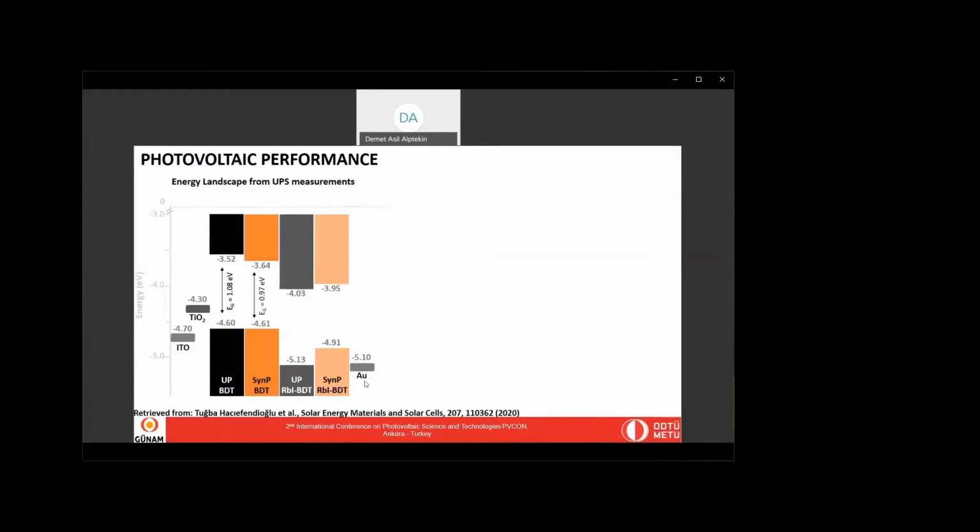This shows that unpassivated quantum dots have lots of surface defects which are healed during that thin film formation, and this leads to a huge downshifting of the energy levels, which is not severe for synthetically passivated quantum dots, which have already passivated surfaces.